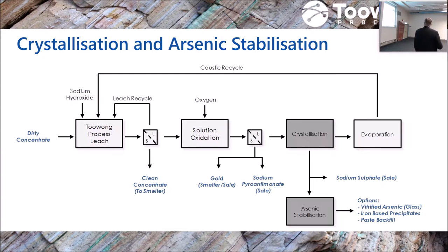The remaining caustic that's left in this stream basically just gets evaporated from a water balance point of view and recycled. So the caustic consumption here is quite low. We're typically only using about 11 kilograms per tonne of concentrate because most of the caustic comes back in the secondary recycle.